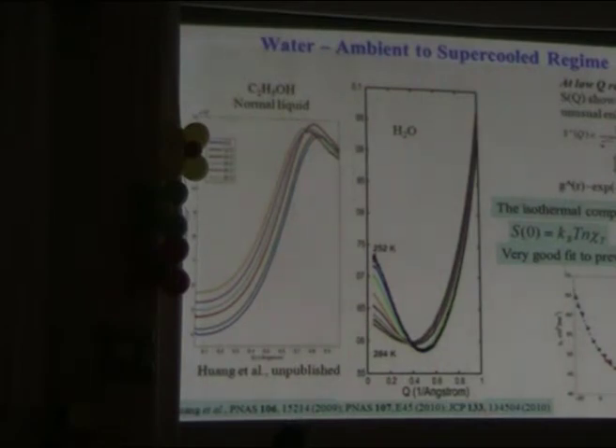On the left here we have a normal liquid, the temperature-dependent small angle X-ray scattering of ethanol, normal alcohol. What we can see is that as we cool the liquid, we just have progressively less and less scattering as the thermal disorder in the liquid becomes less and less. Now, for water, on the other hand, here we go from room temperature, 284 Kelvin, it's a cold room. And as we cool the liquid down to minus 21 degrees C, we see an enhancement of the scattering at low Q transfer.